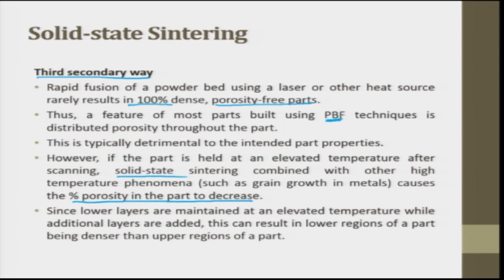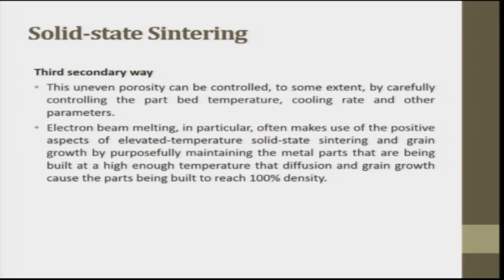So, solid state sintering combined with the other temperature phenomena such as grain growth in metal causes the porosity to decrease. Since lower layers are maintained at an elevated temperature while additional layers are added, this can result in the lower region of the part being denser than the upper region. This uneven porosity can be controlled to some extent by carefully controlling the part bed temperature, cooling rate and the particle size.